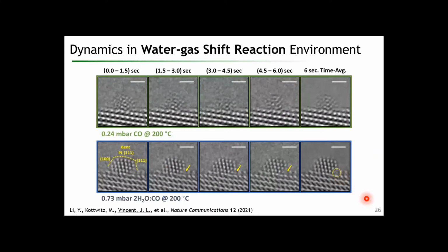So again, we can look at the time evolution of these structures. You can see, like I said, in CO, the structure is completely dynamic. There seems to be a sort of anchoring at the core of the nanoparticle, dead in the center at the interface. The buried core, surrounded by this very dynamic shell, seems to be stabilized.